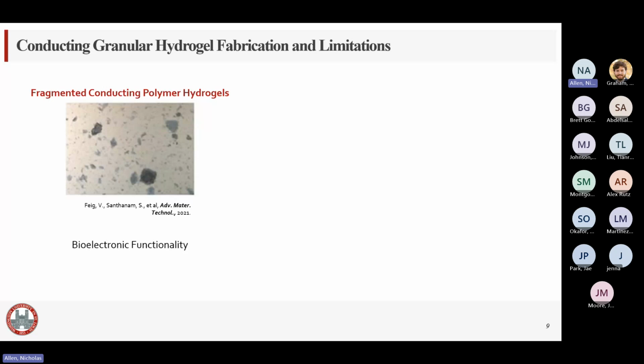Unfortunately, as you can see by the picture, that fragmentation method leads to a wide variety of shapes as well as sizes. And this can impact some of the functionality of the granular hydrogel that we talked about previously. Fragmented shapes can lead to less porous space, so you can have trouble encapsulating and growing cells in the material, and it can also impede extrusion. So it can clog nozzles and needles, or it can require a higher extrusion force, which can impact the accuracy of your print, as well as, if you're encapsulating cells prior to printing, that higher extrusion force can be detrimental to cell viability. So it has fantastic bioelectronic functionality, but still some limitations for the end application.